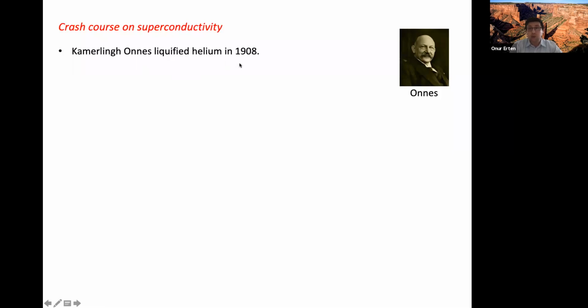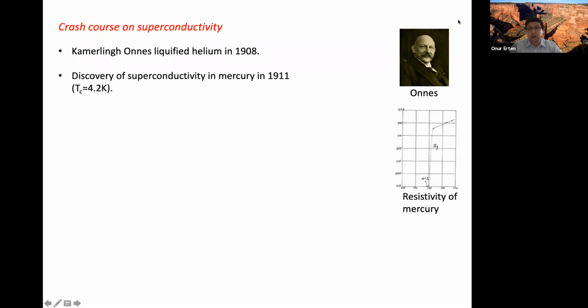This led to experiments for him to go to low enough temperatures that were not possible to go down to before. So he went down to the few Kelvin regime, and he realized that around 4 Kelvin, the resistivity of mercury jumps and goes to 0. This is the original plot from his journal. So this is the first discovery of superconductivity.